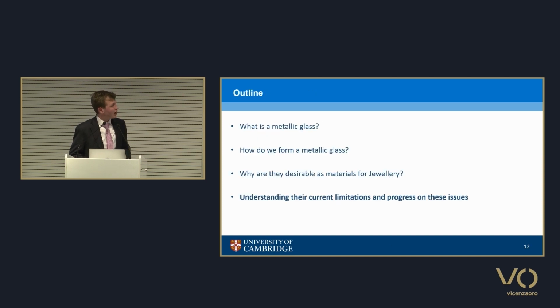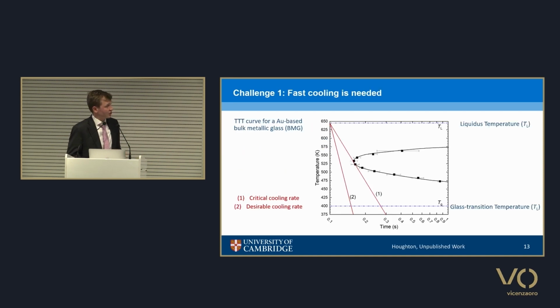Next slide. So we'll now go on to the current limitations and progress on the issues. As we've already mentioned, we need extremely high cooling rates to form metallic glasses. And not only does this create issues with actually forming thick sections and forming glasses in the first place, it will also create many issues with form filling, and so we have to be careful about the design of our castings.